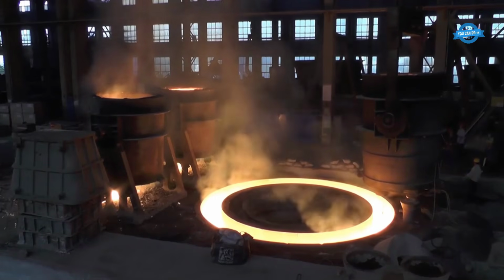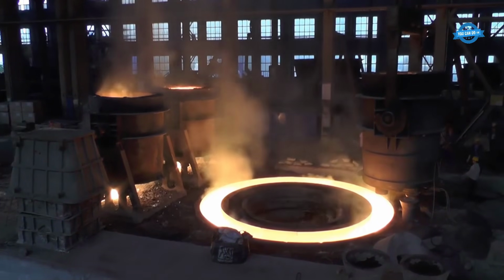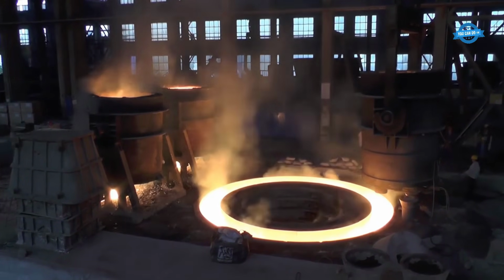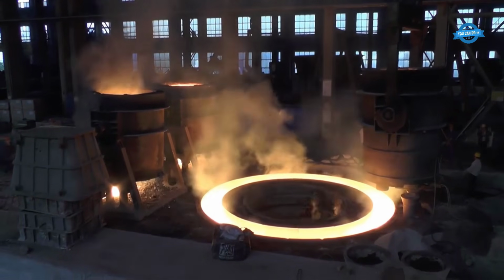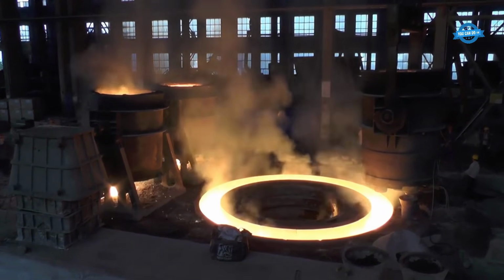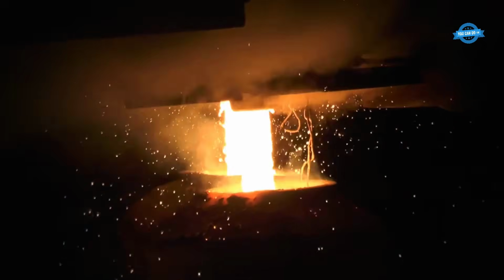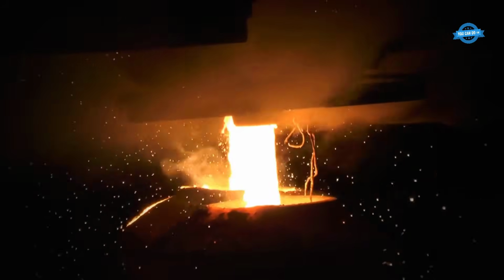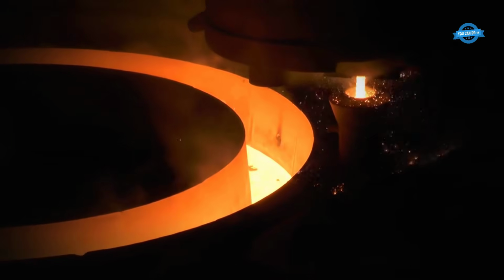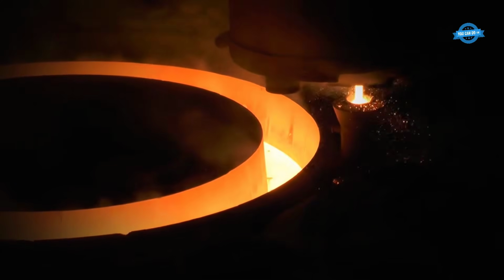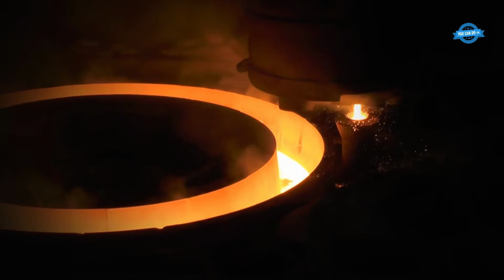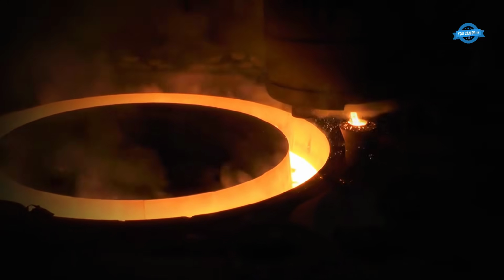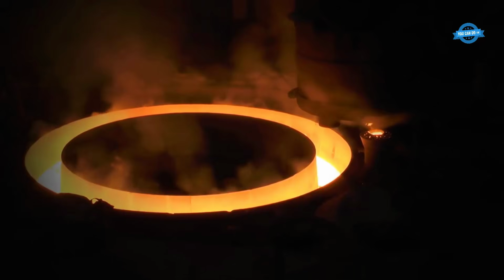Heat treatment. The slag pot undergoes heat treatment, which includes heating to a temperature above Ac3, austenitizing, at around 915 degrees Celsius. Controlled cooling in a furnace is then followed by an intermediate holding phase at 600 degrees Celsius to 630 degrees Celsius. The cooling process continues in the furnace until the temperature reaches 300 degrees Celsius.